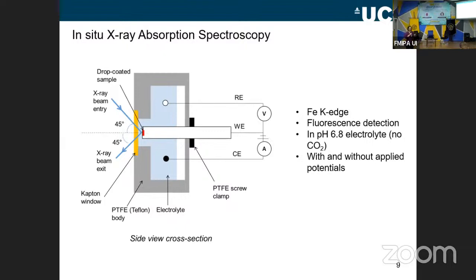And what are we measuring? We're measuring what's called the iron K edge. So basically, we're measuring absorption of the iron species only in the sample. And this will give us information on the iron oxidation state, so whether it's iron 3, iron 2, iron 0. It will also give us information about what it's bonded to and how it's bonded. So it will tell you if it's bonded to sulfur, to oxygen, and what kind of arrangements of the sulfur or oxygen around it. We're going to do the reaction in exactly the same conditions as I showed on the previous slide, at pH 6.8 electrolyte, but with no CO2. And we're going to compare what happens if we don't have a potential and if we do have a potential.